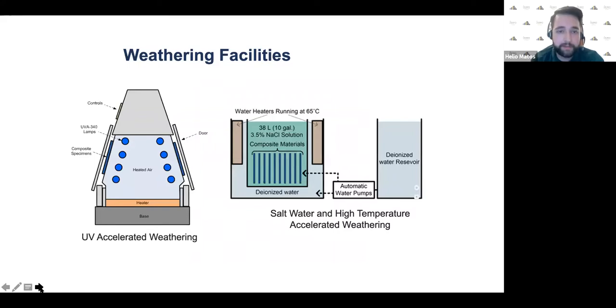And the next slide is our 2 weathering facilities. The first one shown on the left is an ultraviolet weathering facility. So we place our material in there to simulate exposure to sunlight at an accelerated rate. The acceleration rate depends on the specific material that we're testing. But what we can also do, shown on the right, is accelerated weathering through water infusion of salt water. And in this diagram, we have a multitude of variations of this facility. The one that is shown here is just for